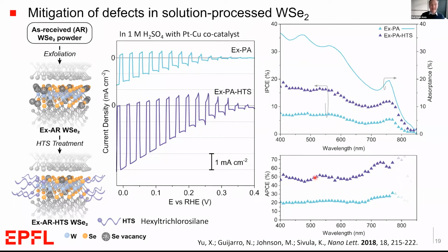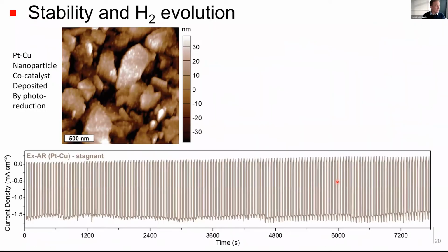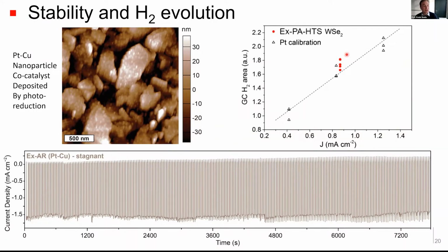So despite the fact that we're processing these using solution-based processing techniques and making large area devices, we can still get quantum efficiencies that are similar. Moreover, we can show that the performance is quite stable for hydrogen production, and we can measure the hydrogen produced using a gas chromatograph and see that, yes, we have 100% Faradaic efficiency for the hydrogen evolution reaction.